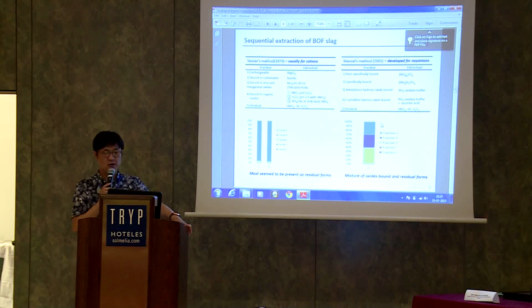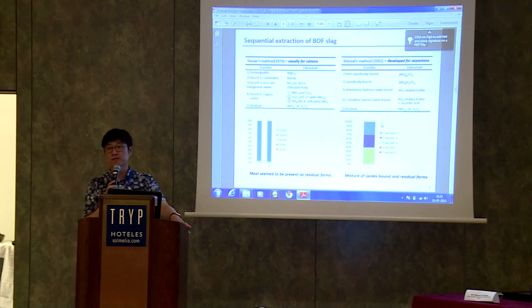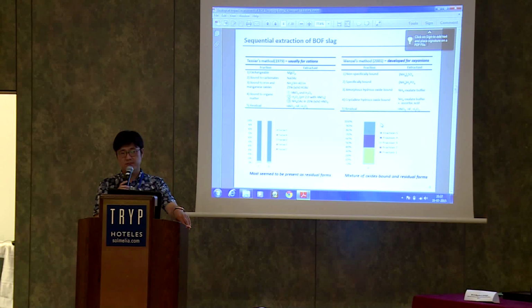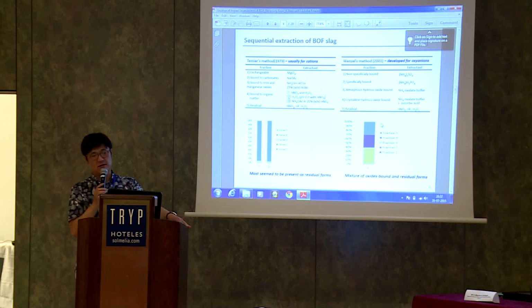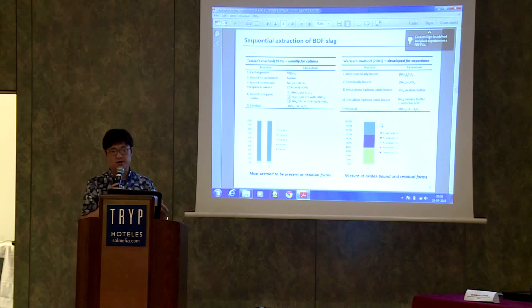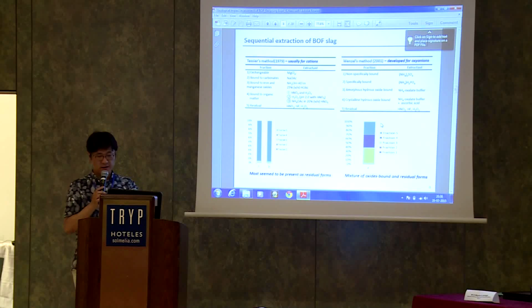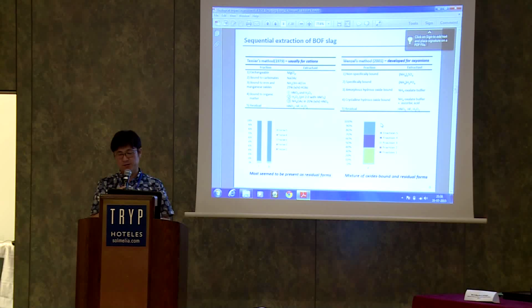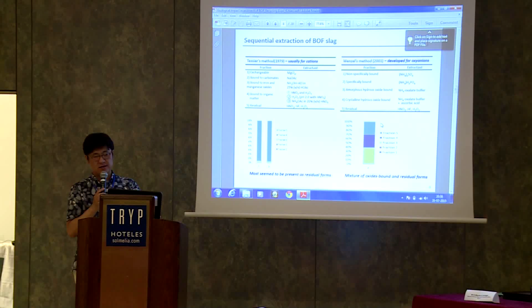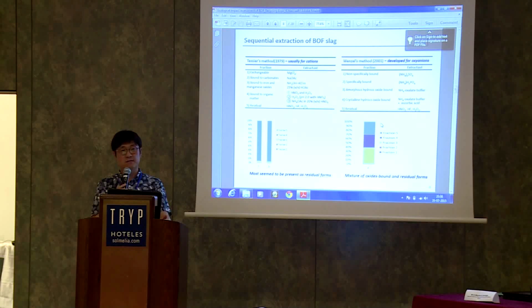Next, I'd like to know the chemical forms of each heavy metal or fluoride in the slag. So I performed the sequential extraction test. There are many sequential extraction methods available in the scientific field, but I used two of them. The first one is Tessier's method, firstly developed for cations, so usually heavy metals. And I also used Wenzel's method, developed for oxyanions such as fluorine or fluoride or arsenic. As you see in this figure, based on Tessier's method, most is considered as a residual fraction. And by the Wenger method, most is present as oxide forms or residual forms, which means the fluorine or zinc are present in the slag as non-labile or less labile forms.